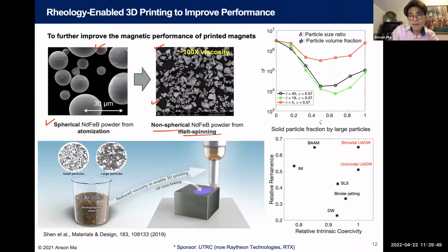Now, if you look at the particle morphology, they're much more jagged, right? So it's more irregular shaped. And then if you look at the viscosity, when you disperse it at the same volume fraction in the resin, in the photopolymer, it's actually 100 times more viscous. So then we have big trouble in printing that stuff. So then what do we do?